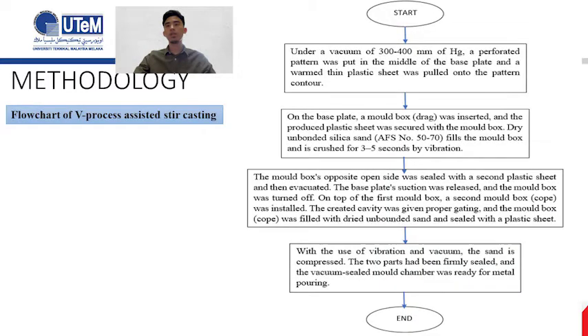And then for the flowchart of the V-process assisted stir casting, start with a vacuum of between 300 and 400 mm. A perforated pattern was put in the middle of the base plate, and one thin plastic sheet was pulled onto the pattern contour. And then on the base plate, a mold box was inserted, and the plastic sheet was secured with the mold box. Dry unbound silica sand fills the mold box and is compacted for 3 to 5 seconds by vibration. And then the mold box's opposite open side was sealed with a second plastic sheet and then evacuated.